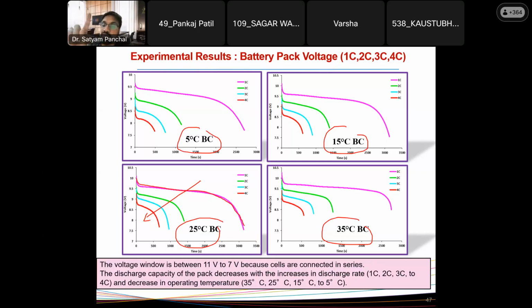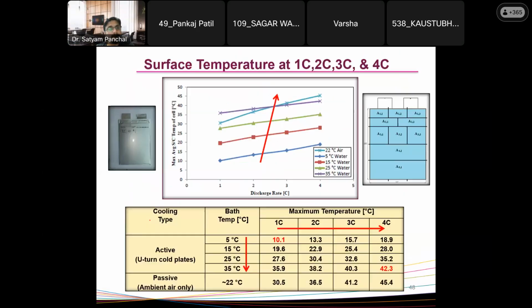I did not go below 5 degrees centigrade because then we had water bubble issues, and we had to add glycol, so a water glycol mixture, but I did not do any 0 degree or negative temperature experiment. But we have a facility for thermal chamber inside the laboratory. We have a refrigeration unit also, and we did those experiments also.